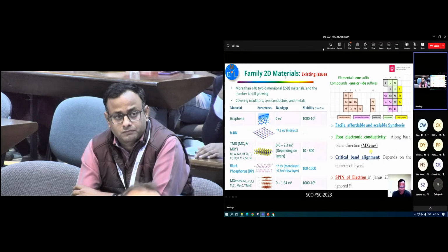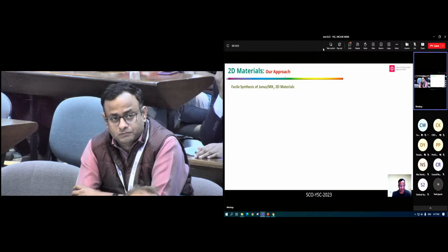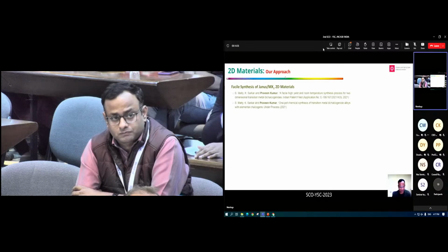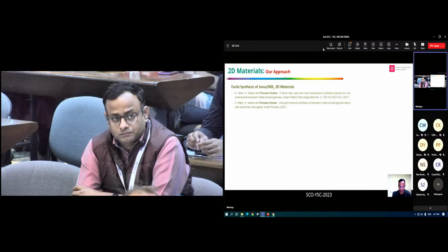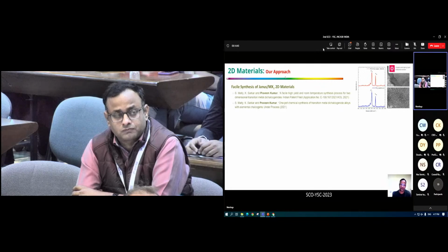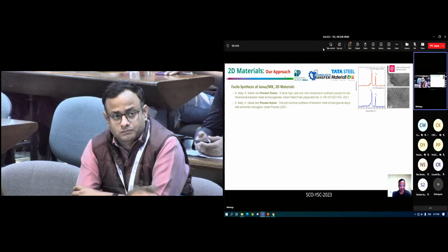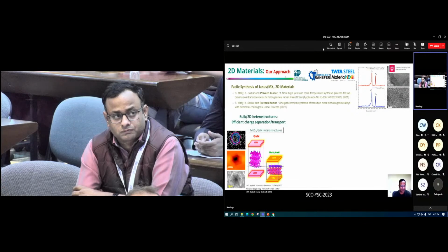We have also worked on the critical band alignment, and also the new topic which we have started at IISc, to use the spin of the electron, which has been ignored till now. As far as the facile synthesis is concerned, we have recently developed two room temperature chemical processes, by which you can get this 2D material in a layered exfoliated high quality, and you can see the comparison between the industrially available material and the method which we have made. So we have filed 2 patents.